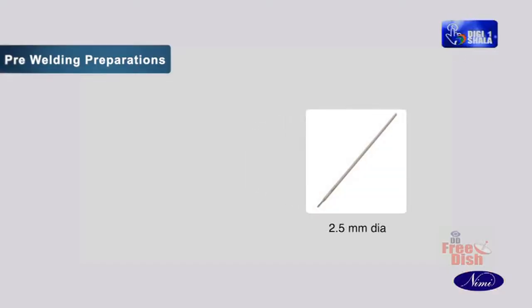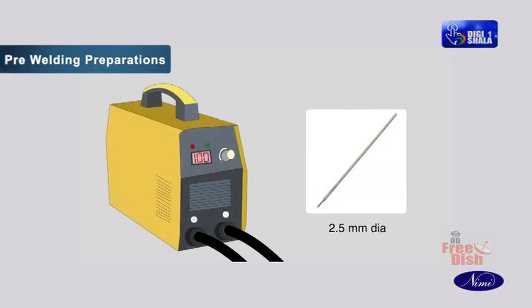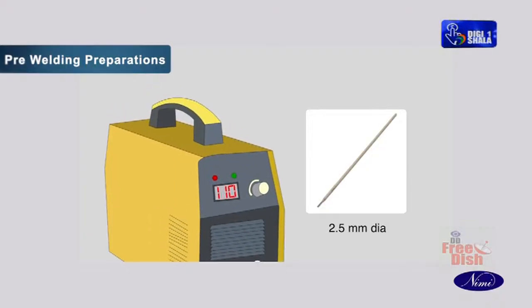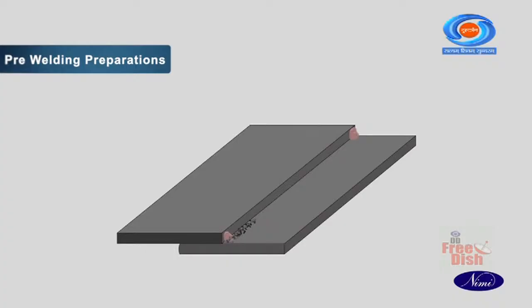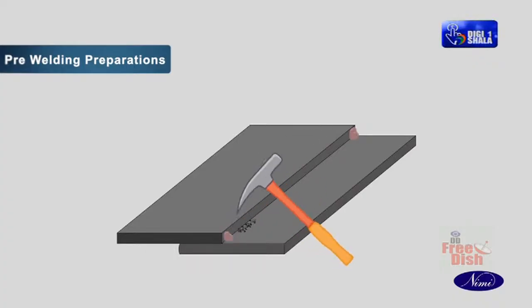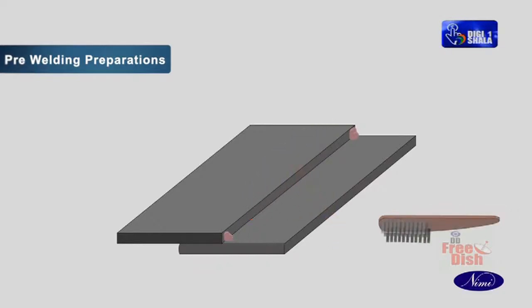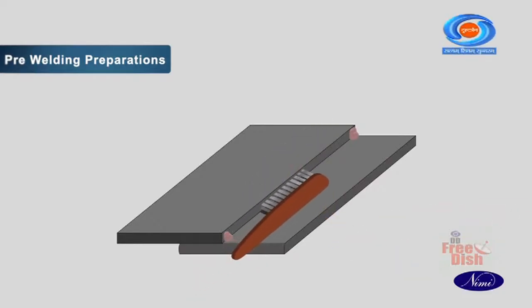Use a 2.5 mm MS electrode with 120 amp current for tacking. Set the lap joint in a flat position and remove the slag with a chipping hammer and clean the weld with a steel wire brush.